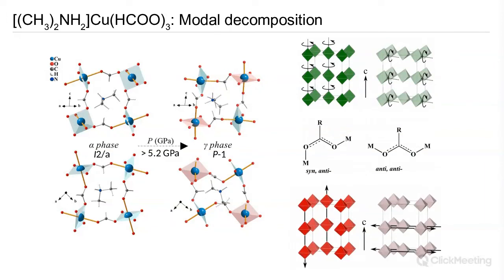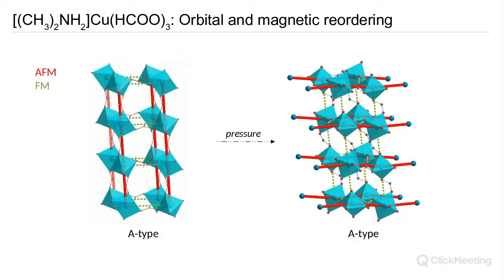They're degrees of freedom that the system can explore. The resistance to those deformations is originating in the desire for formate to be bonded anti-anti. This is a hypothesis. This would be something that would be interesting to explore in the future. And of course, the other implication of this phase transition is that it in principle has a profound impact on the orbital and magnetic reordering.